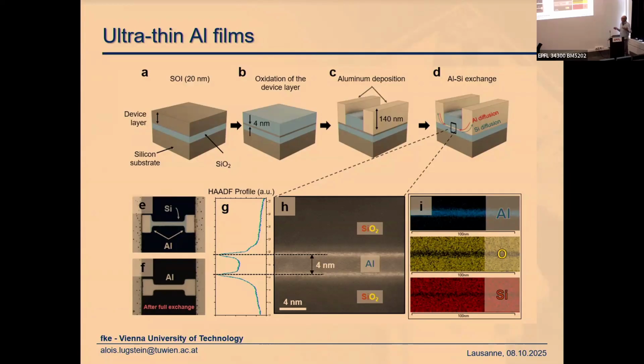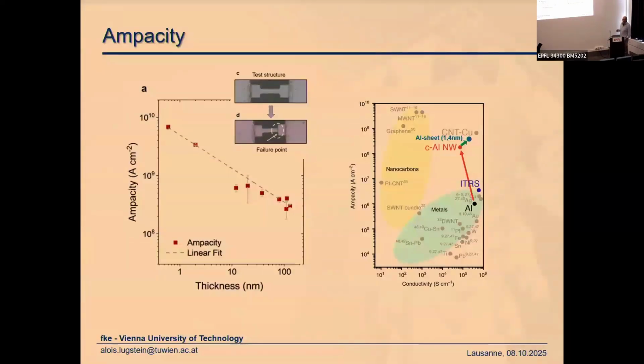So we can make sheets which are 20 nanometers thin, 4 nanometers thin, 1 nanometer thin, which is the thinnest up to now. And a nice feature of these structures, which is not well understood now, is that when these sheets get thinner and thinner, the ampacity, so the maximum current that you can drive over these structures before they fail, so finally they crack, get one crack. It's not that they explode, they just get one crack. This ampacity increases when the sheets get thinner and thinner. And compared to what was predicted in the ITRS roadmap, you see that we are about 2 orders of magnitude above the critical current capacity, or the ampacity, for aluminum.